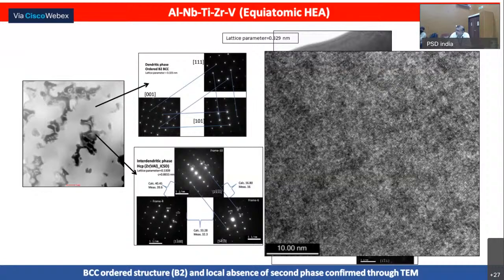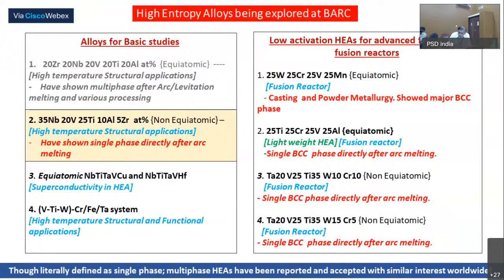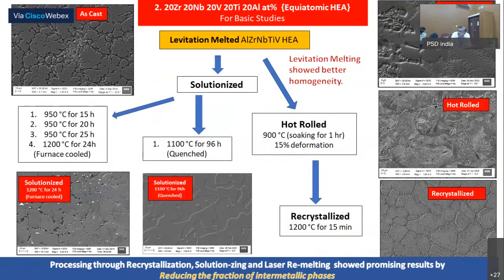But at atomic resolution, you don't see any ordering structure. Whatever little you see is because of the strain matrix, which is not allowing a very clean picture. So the phase we have found is a single phase material. We went for that and started looking into the material.